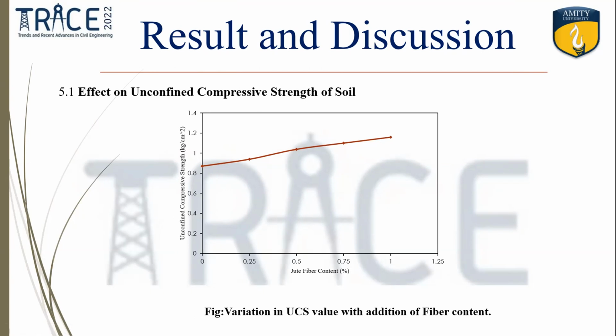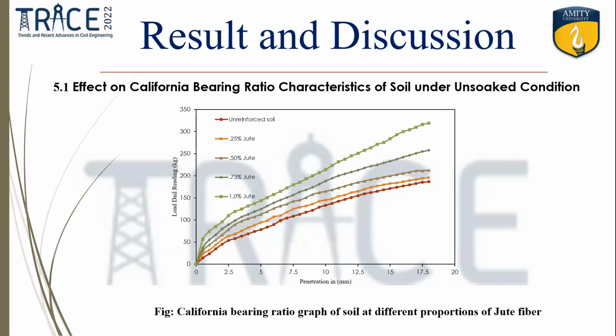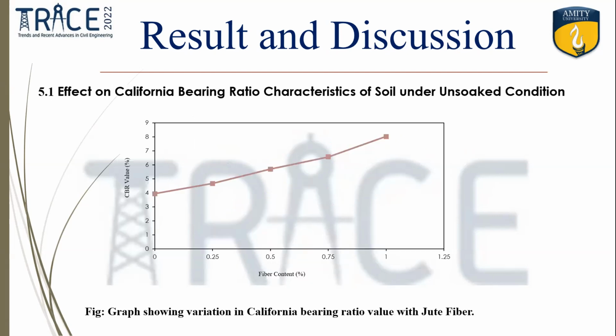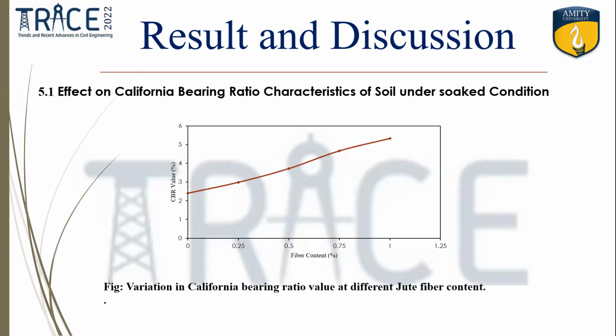Next slide, please. These are the graphs which represent the CBR value under unsoaked conditions. As we can see, the highest value is obtained for 1% and the lowest is obtained for unreinforced soil. Next. This graph also represents the CBR value with respect to the fiber content, and the maximum is obtained at 1% and minimum at 0.25%. Next slide.